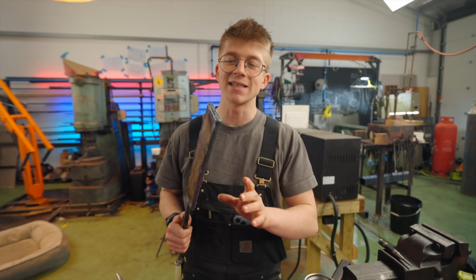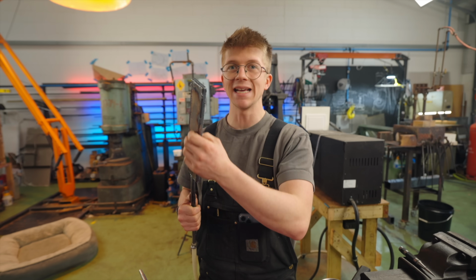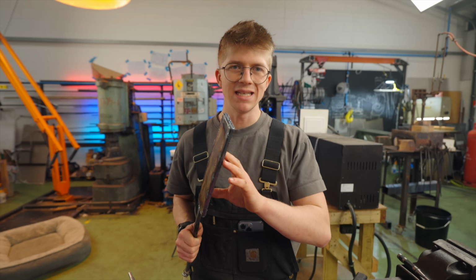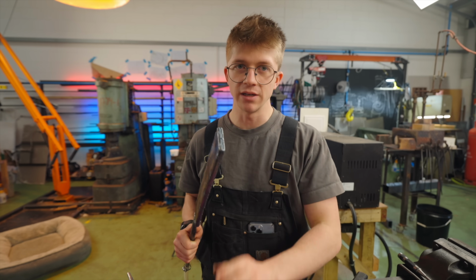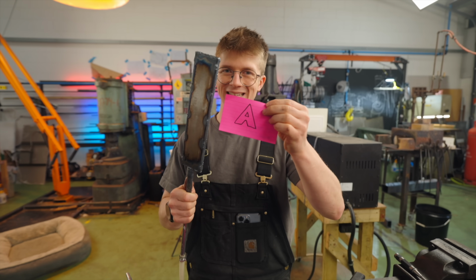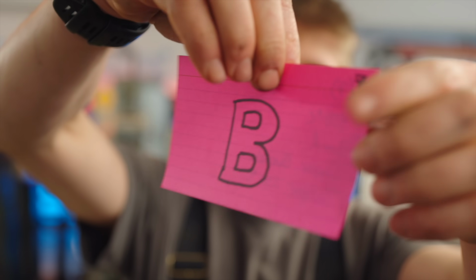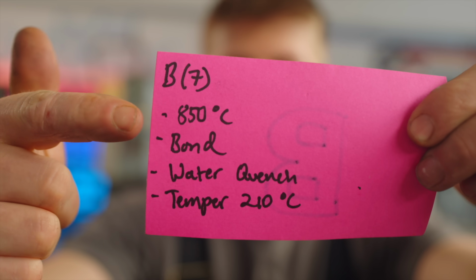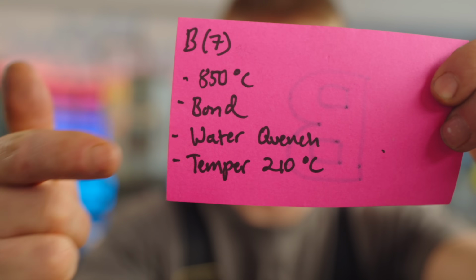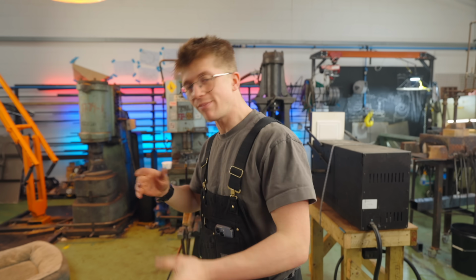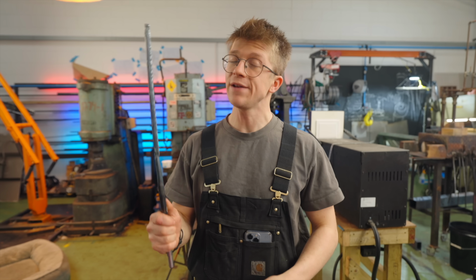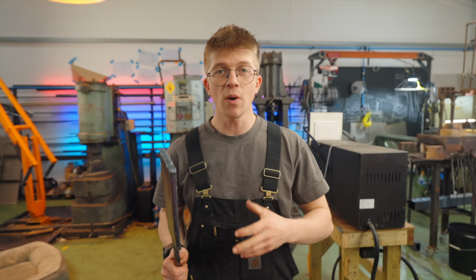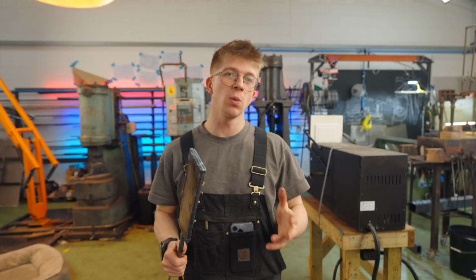And I reckon that, in addition to the steel being encased in this box, is the reason why we didn't get the hardness that we ideally wanted. To be prudent, of course, we're testing it again. Experiment B is going to be changed in this way. Same bonding temperature, same bonding, but a water quench. The water is going to rip the heat out of this thing way faster than the oil will, which is why typically for knife steels, you don't do a water quench because it cools it too fast and can cause cracking, breaking, warping. I want to see if that will now get us the hardness we need in the core.